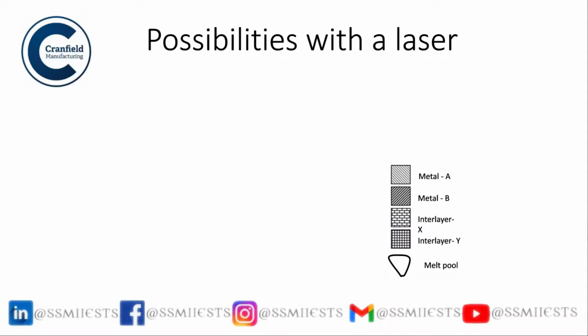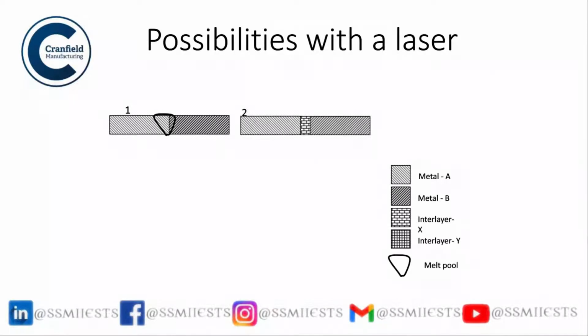So, possibilities with a laser. With this particular slide, I would like to show the different ways you can apply heat in a manner that you can form the weld pool at a particular location. You can see these are two alloys, A and B, and you can have a weld pool where you can have more of A, less of B, more of A, or full of, say, an interlayer X, because it is required when you have dissimilar joining. I will explain that.